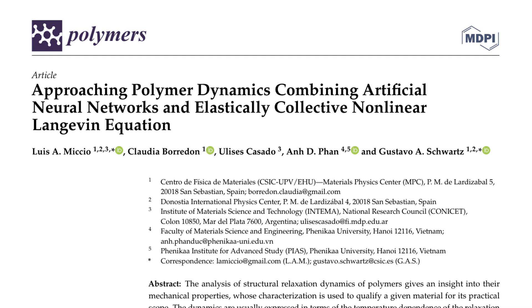The paper mentions the importance of accurately encoding the chemical structure of the polymers using SMILES representation and converting it into binary matrices for input into the ANN. The architecture of the ANN includes convolutional layers to extract relevant chemo-structural features and fully connected layers with leaky ReLU activations. The hyperparameters of the ANN are optimized using a mini-batch gradient descent technique with an Adam optimizer.